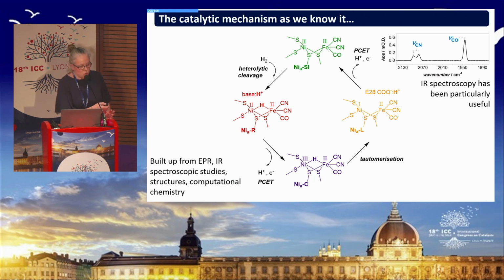And as you'll well recognize from other work in catalysis, the CO and CN ligands at the active site of hydrogenase provide ideal probes in the infrared for looking at the active site and are very sensitive to any changes in electron density on this site, meaning that we can track every single intermediate in catalysis via the CO vibrational band position.